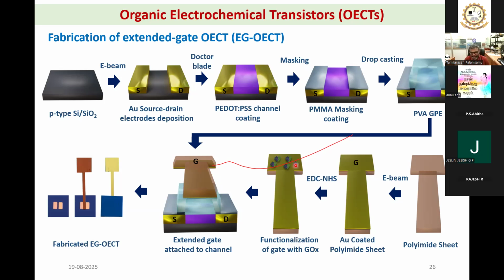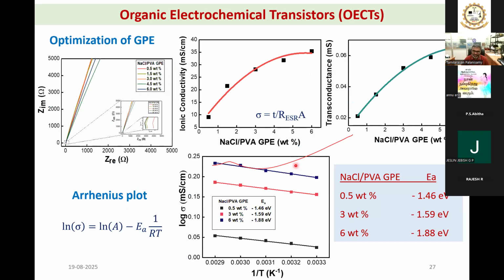It should have a very high conductivity. That is very important. There should be a high amount of mobile phase. There should be no electrolyte depletion at any point, in any case. So I can put a lot of NaCl salt, but the problem is when you put too much NaCl and too much water, the electrolyte will not be a gel polymer, it will be a liquid electrolyte. So I need the gel shape, the structural integrity should be there, but still I need a better electrolyte conductivity, ionic conductivity. Okay, so this is what we have optimized in this case.